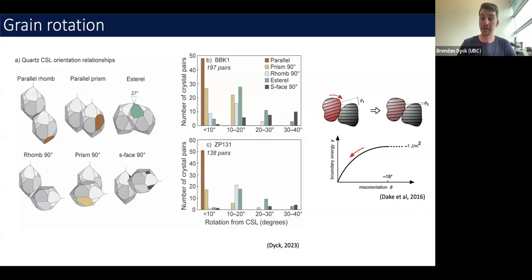Now, an interesting feature here is that grain boundary energy drops off to a minimum when they become parallel with each other, or when they come into the lowest energy permissible relationship on those two planes. And the driving force that might actually cause rotation of these crystals drops off as we get closer and closer to our low energy relationship. That might explain why we still see a high frequency of crystals that aren't that close, or within 10 to 20 degrees, of these low energy relationships. And that's still occurring at a far higher frequency than what random interactions would predict.